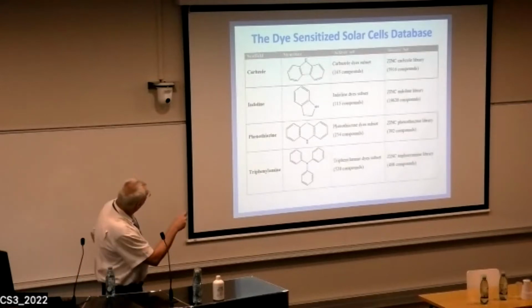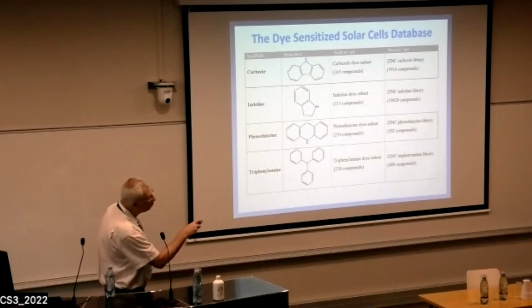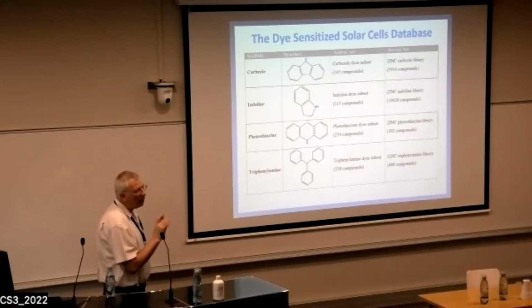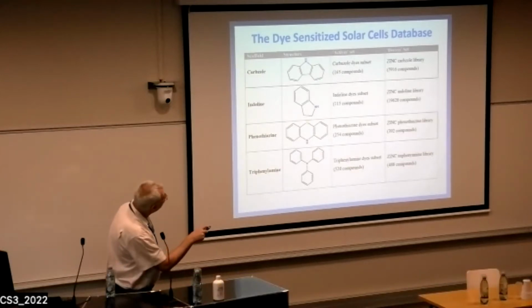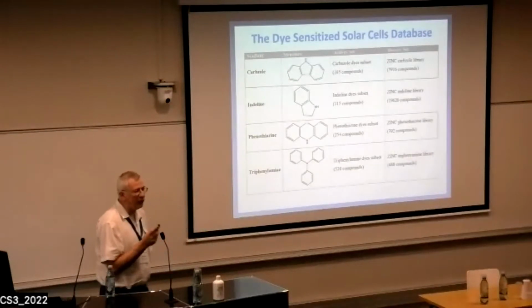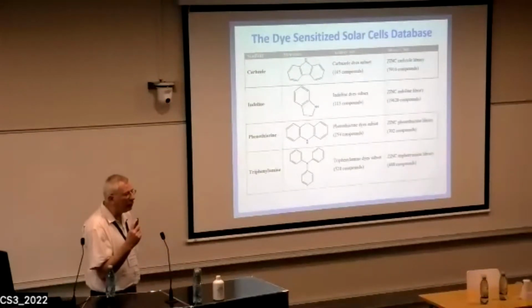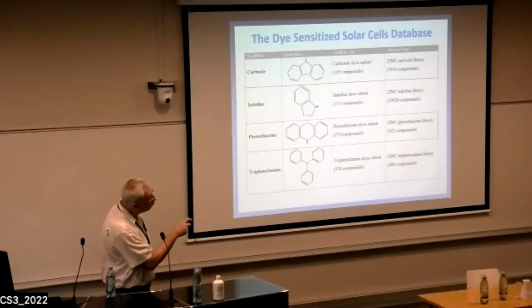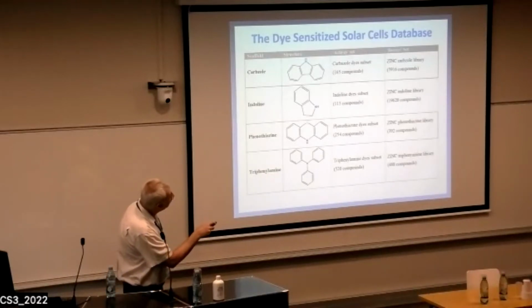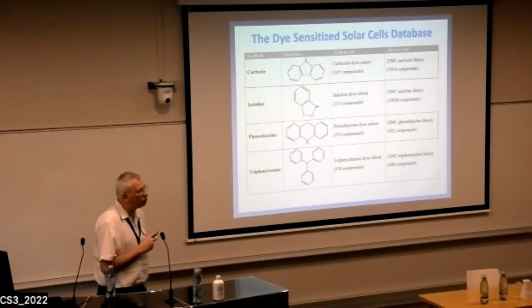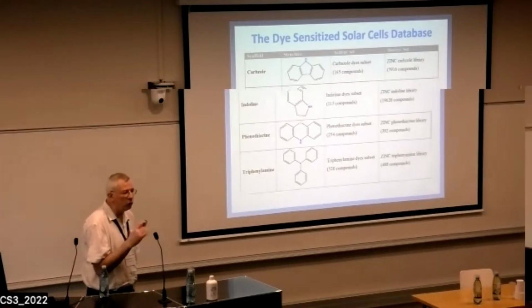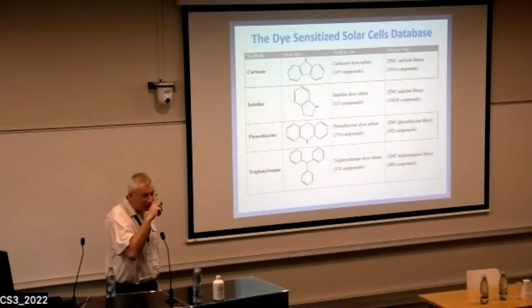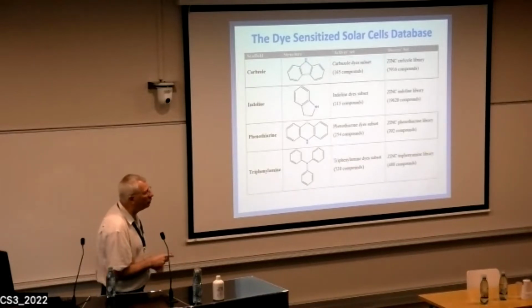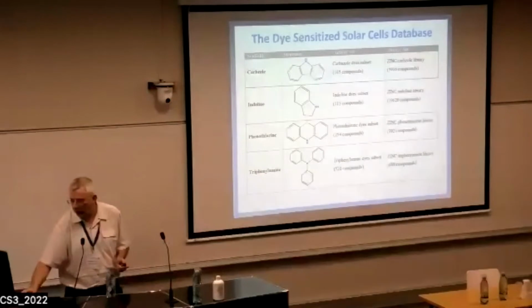and we built a model for these 4 families because these were the most populated. So here's the number of compounds in each family, and here's the number of compounds we retrieved from the ZINC database in order to validate the model. I'll get to it in a second, but it's important to say that we validated our models on compounds having exactly the same substructure as the dyes. Otherwise, we would run the risk of cheating ourselves, and self-cheating is nice, but we don't want to do it.